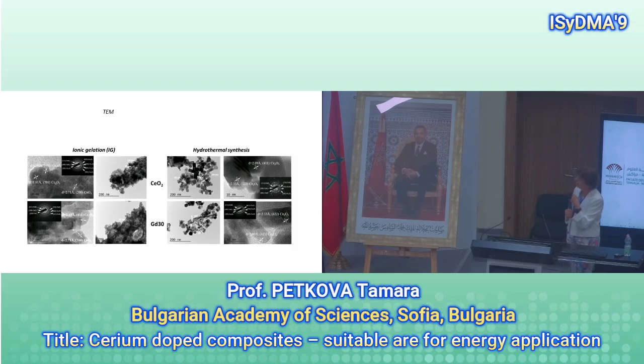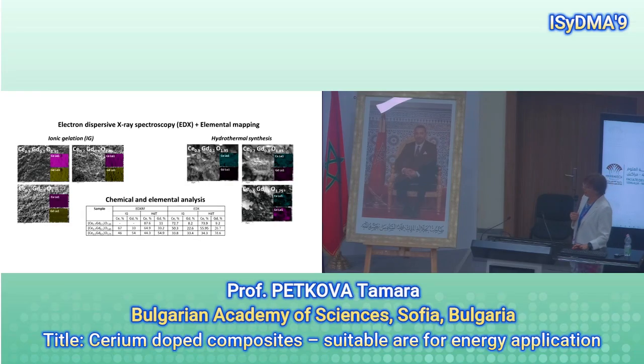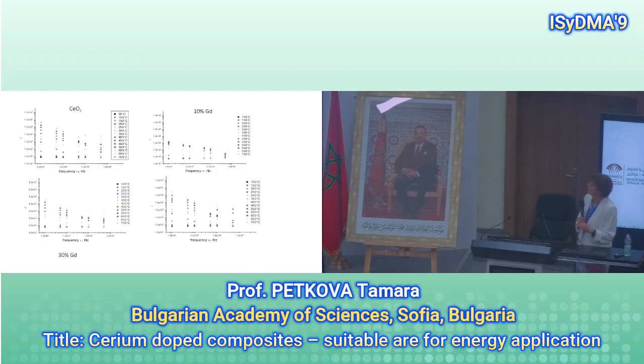The interesting thing here is that with increasing gadolinium content, we obtain some nanorods. And the number of these nanorods increases as gadolinium increases. We think that this is due to the conditions of the synthesis, and if we change the temperature, for example, or the pressure and the time, maybe we will see a different shape, as we've found in the literature. From the data obtained from energy dispersive X-ray spectroscopy and elemental mapping, we saw that they are homogeneous and the composition is close to the initial.